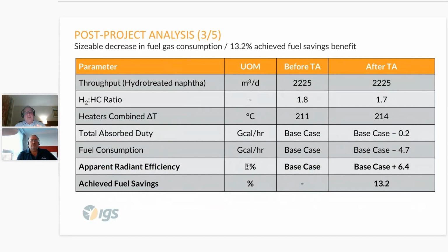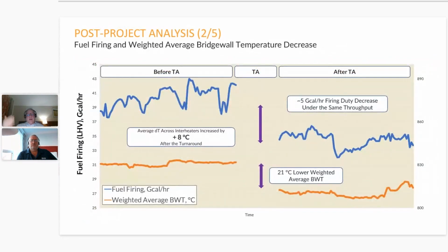There you go. But the point is that previous slide was all about the data that the customer supplies us, and we'll do some post-turnaround calculations because that bridge wall temperature is no longer a production limit. You're not pushing too high of a temperature even into the convection section where frankly customers have done inadvertent damage to their convection sections just by operating at those high temperatures.